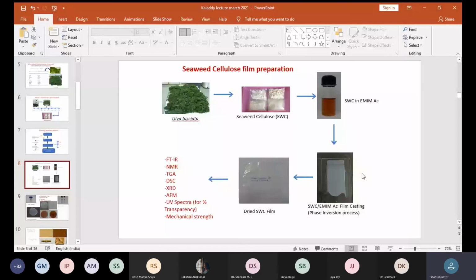This is the final film. You can see we can literally write on it with a normal ballpoint pen. This is the cellulose film derived from SWC without any aging. The film is dry and very rigid, comparable to commercial polyethylene film, and we did all kinds of characterization to make sure this film is good. And we did the optical transparency. They want to see the fruits or whatever they are covering with your film, so when the film is very transparent, they say that is good. So we did the optical transparency, and if we are getting a good one like this, which is optically transparent, we can consider this as a food package film.